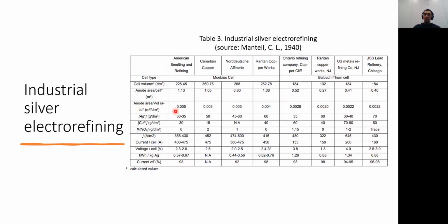For me, the Moebius cell is much more efficient, because we can see from this Mantell data, which I put into perspective with these calculated values of the anode area and anode area per cell. So in the Moebius cell, the area covered by electrolyte is higher than in the Balbach-Thum cell. So in short, in the Moebius cell, we need less electrolyte than the Balbach-Thum cell, or we can put more anodes to be processed than in the Balbach-Thum cell because it has twice the area. So for me, it's a very easy option. The Moebius cell is the most robust among these two.